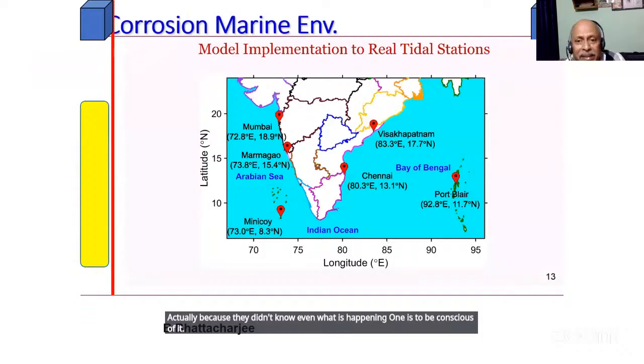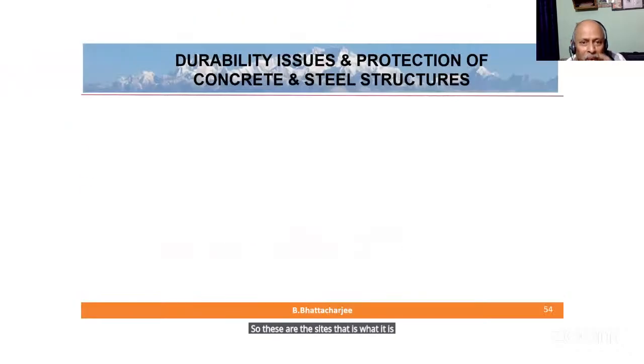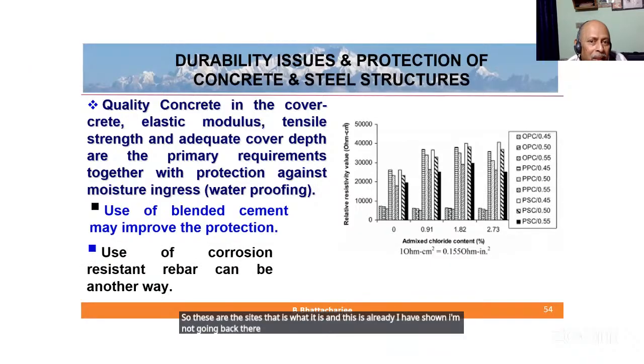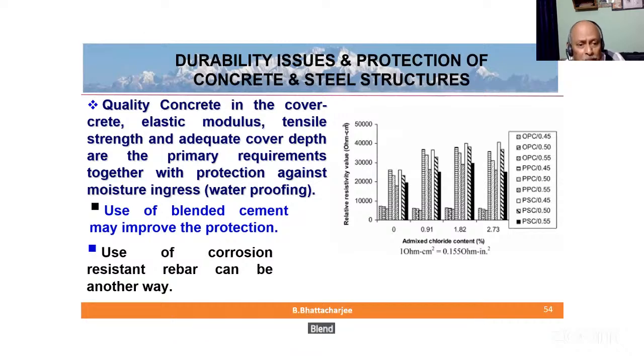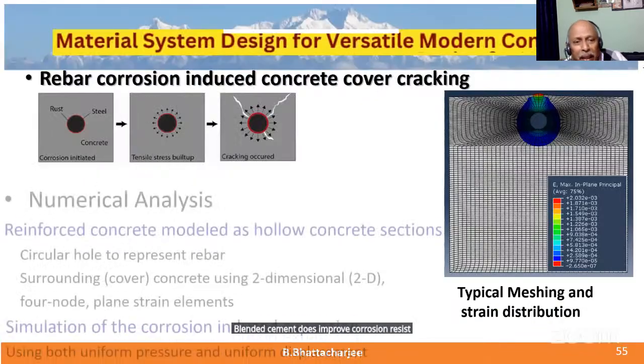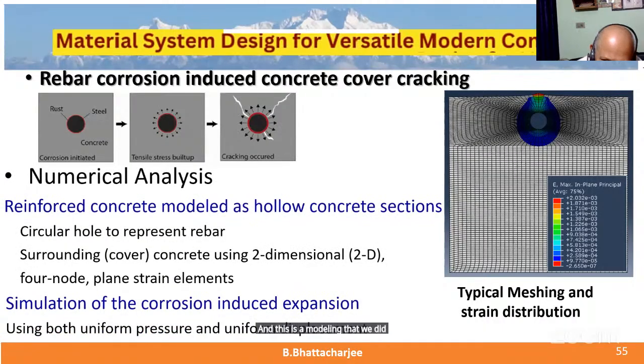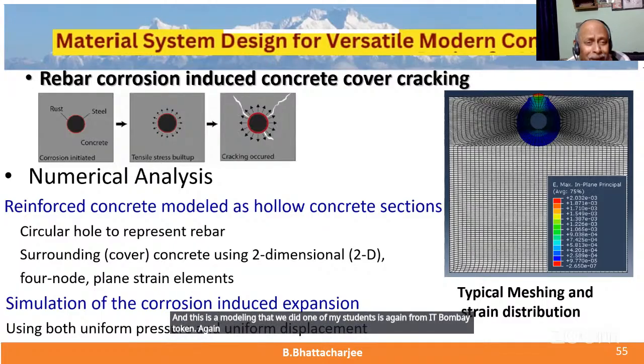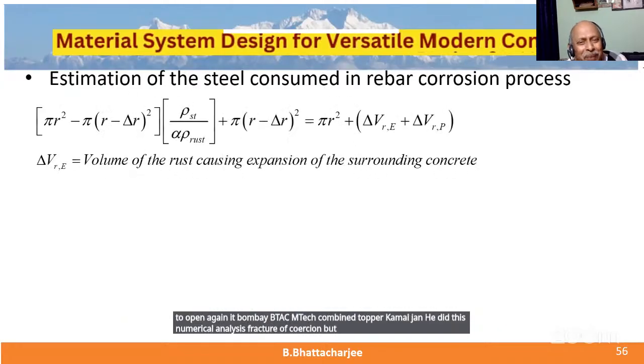So these are the sites, and this I've already shown, so I'm not going back there. For durability, of course, the quality of concrete cover, elastic modulus, and tensile strength are important because fracture depends upon tensile strength and elastic modulus. Blended cement does improve this. Corrosion resistant rebar can help. And this is the modeling that we did. One of my students, again from IIT Bombay, the BTech MTech combined topper, Kamal Jain, did this numerical analysis of fracture due to corrosion. But unfortunately, there is no lab data to verify this.